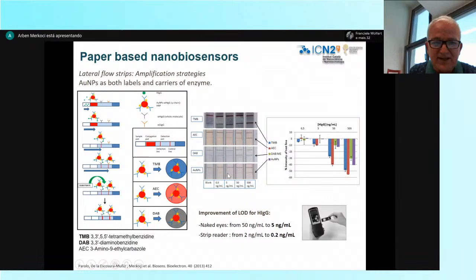For example, you can see here from bare gold nanoparticles to the one modified with TMB, there is a clear change in the signal that you can see also in the change of the sensitivity here in this diagram. So in this way, we can use lateral flow with much more sensitivity, even decreasing the detection limits.